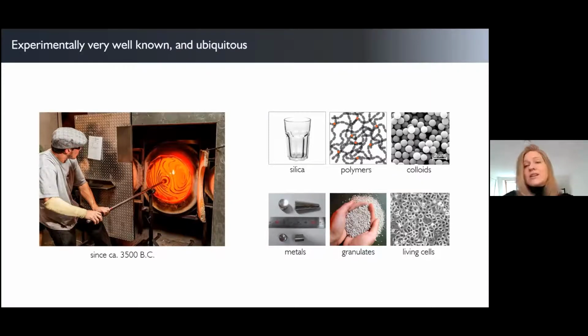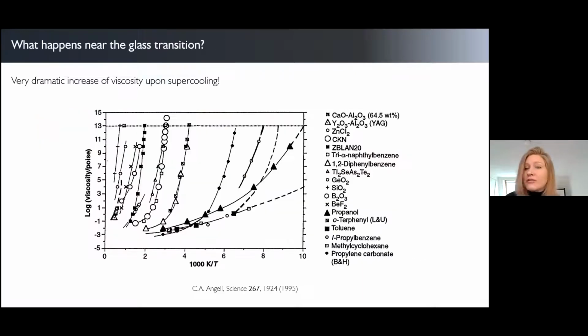But theoretically, there's actually quite a bit that we don't fully understand yet. There are many interesting and puzzling aspects of glass formation from a theoretical point of view. But one of the most striking features is that as you go from a liquid to a glass upon supercooling, the viscosity of the material increases very dramatically by many orders of magnitude upon only a small decrease in temperature.